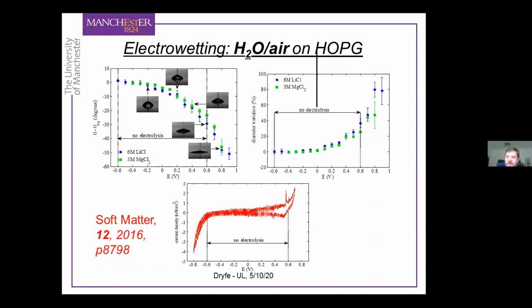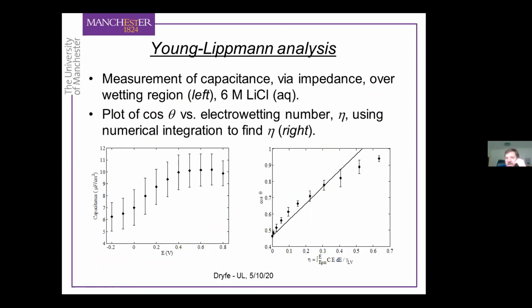And just to emphasize that we think, at least, this is a capacitively driven phenomenon because we're in a range of potentials where we have little or no Faradaic effects going on. So we think that this is purely driven by the change in the capacitance of the interface. That's what drives the contact angle. And then we can do a standard Young-Lippmann analysis. This type of electro-wetting has been known for many years. We can independently measure using impedance.